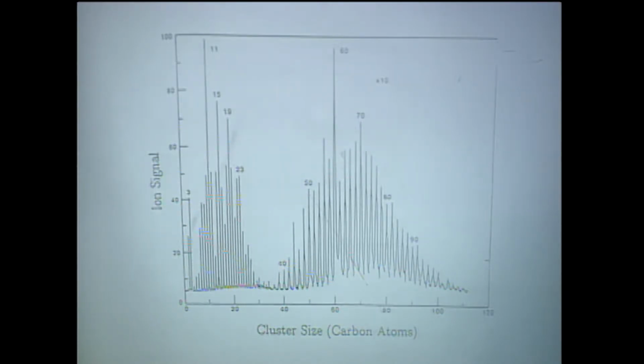and then a secondary peak over here around C70. Now, the Exxon group that published this paper were very excited about finding this series, where the peaks were all separated by two. But they had no idea that this was related to anything new, that it had anything to do with closed shell molecules or fullerenes or anything. So they did a wonderful piece of work, but they sort of missed the boat, and science is sometimes a little cruel that way. But the group at Rice University were doing a similar experiment, and they were doing it for totally different reasons.